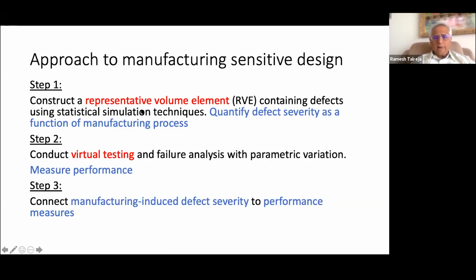The first is to represent the internal structure of a composite when it has been produced, having manufacturing defects. And because the nature of the defects is not deterministic, you have to do statistical simulation of that. Now, the novel part of the approach that I have been taking with my students is that we want to quantify those defects. So with the statistical simulation, we have added an aspect that will come up with the defect severity as a measure of the defect.